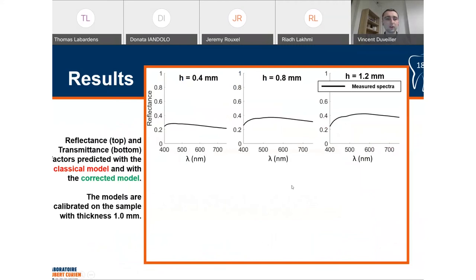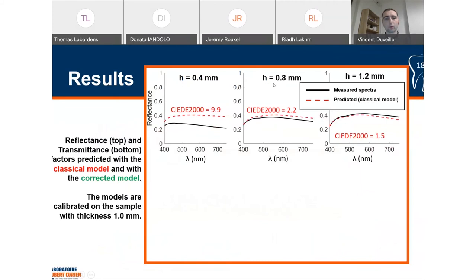Here you can see the measured reflectance factors for our samples with thickness 0.4, 0.8, and 1.2 millimeter. And here the red dashed curves represent the predicted reflectance factors using the classical Kubelka-Munk model, the one which does not take into account our observations on the effective measuring geometry. The color distance between the red dashed curves and the black curve is written here in red. So for the sample with thickness 0.4 millimeter, you can see that the reflectance prediction is totally aberrant. The curves are totally different and the color distance is much higher than 2 units. So this prediction is wrong.